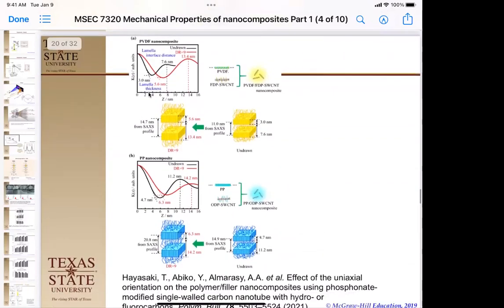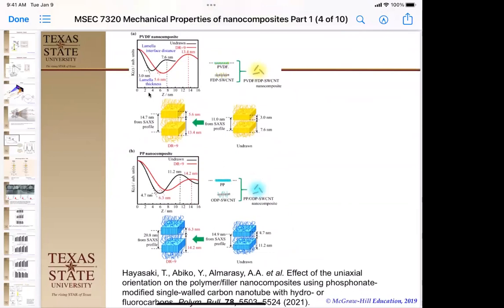Okay. So what they also ended up doing is looking at whether the polymer was ordering or the carbon nanotube was ordering by looking at X-ray. If we look at our X-ray here, these are actually X-rays. And what you're going to see is that the polymers, as they crystallize and are being drawn out, form these little platy lamellae, little crystals with these defect ranges or rubbery ranges. And we can see that the distance changes from about 11 nanometers to about 15 nanometers. Now, I don't know if that's big enough to fit one of those nanotubes in between those lamellae, but it did have an effect on the draw.